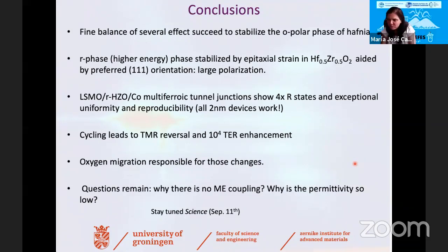Thank you. We have another question by Akash Badnagar. Analogous to thin ferroelectrics, are fractal domains also visible? Well, we haven't seen domains in hafnia. I don't think a lot of people have seen natural domains in hafnia, but indeed fractal domains are forming in ferroelectrics. In hafnia, it's difficult to observe them. As you say, the natural domains would be very small. They would be very difficult to observe. I showed a slide on artificial domains. Those are typically large because you made them with the tip of an AFM, so you don't have the possibility to then observe the naturally formed fractals.